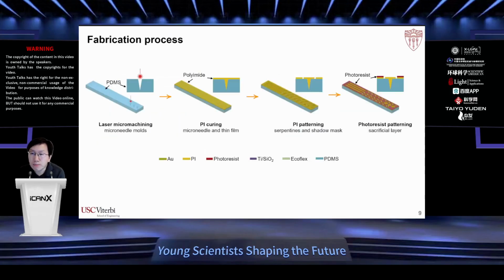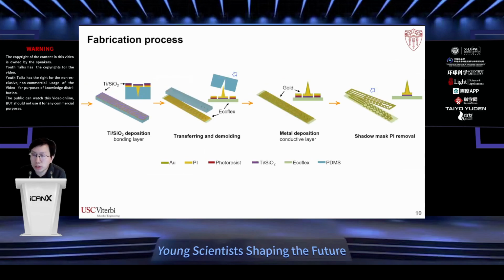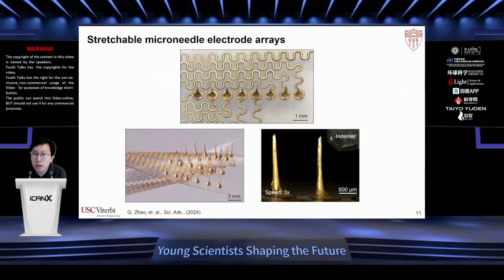So that's the idea. We fabricated these stretchable microneedle electrode arrays using a hybrid method combining laser micromachining, photolithography, and transfer printing. The result of this process is that we can make polyimide-based microneedles coated with gold to make them conductive.